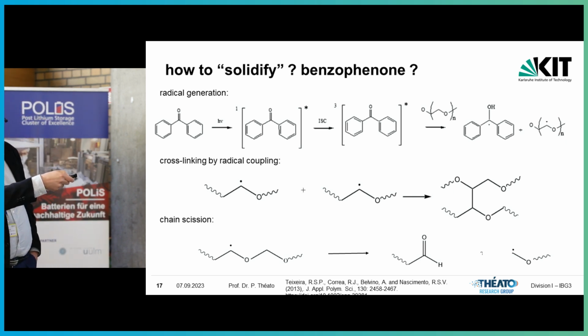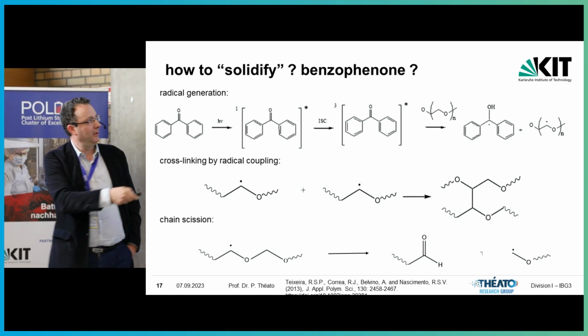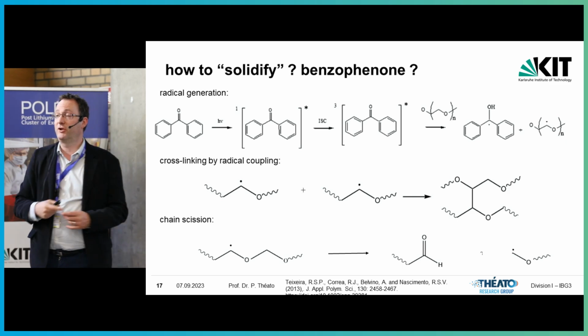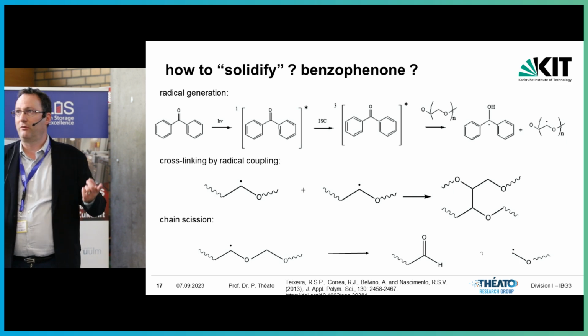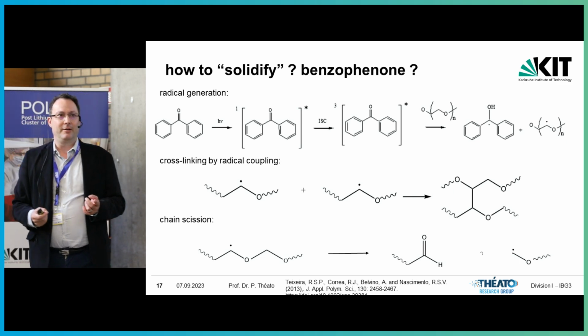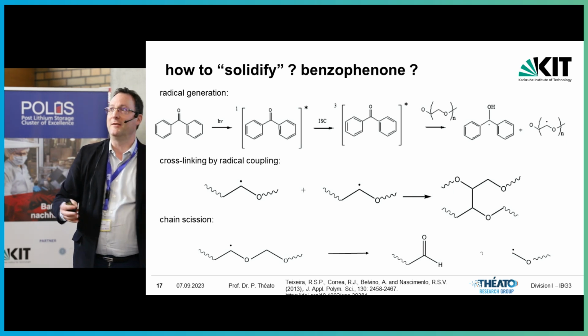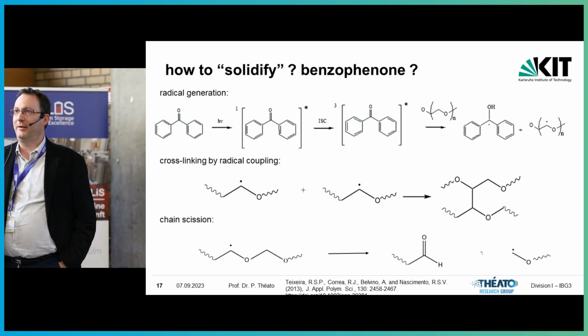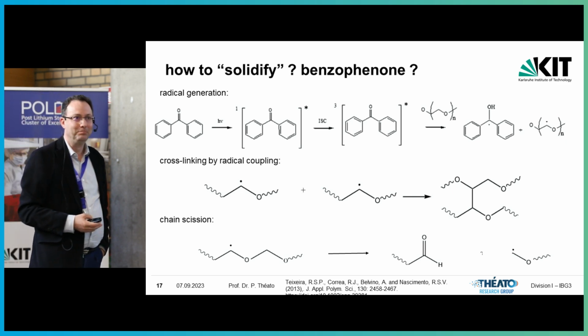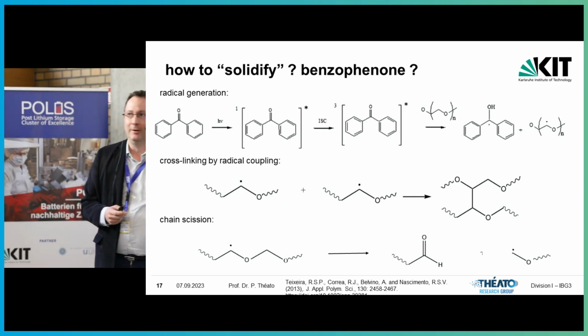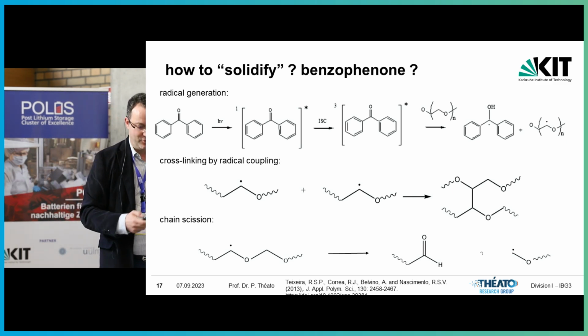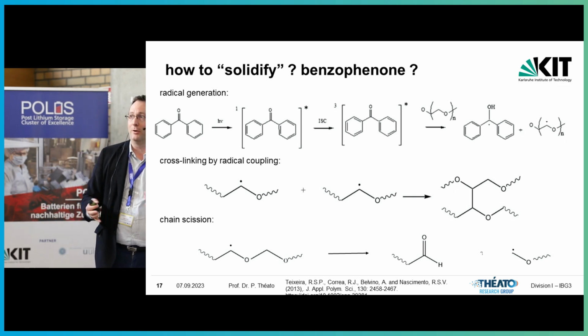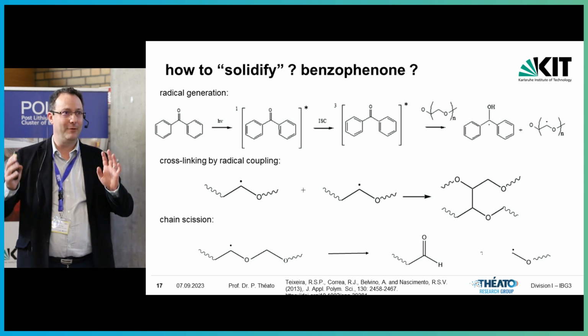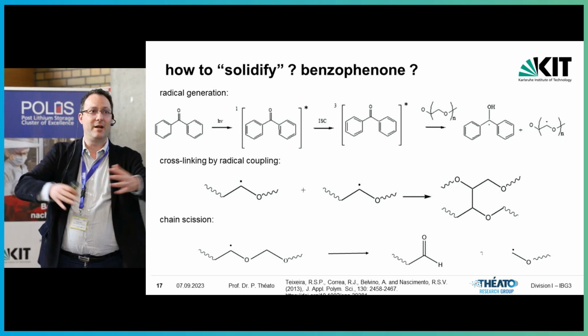This bond here can cleave homolytically. You form an aldehyde and another radical. Okay, so this radical, of course, can do a cross-linking again, but you have done the chain scission before, so you don't change the cross-linking density at all. And now I don't understand, you know, what the overall cross-linking density in such a film is. The only way to get this is because you use very high benzophenone contents, 5 mole percent or 8% or whatever. So you just exhaust the system to make sure you get sufficient of these bonds. But you get plenty of other reactions as well, and I don't know whether this is helpful. So that's something I would like to learn, and you can throw stones at me at dinner, okay?